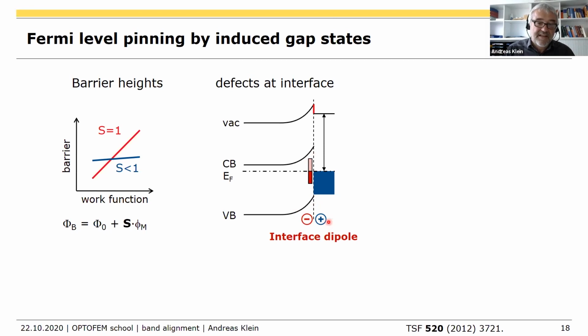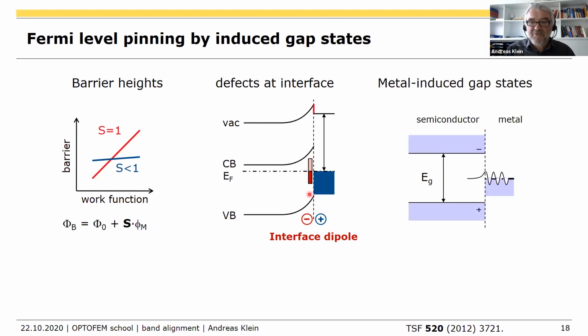If you have an interface dipole there, your vacuum levels are no longer aligned. You have a potential drop there, and this modifies the barrier height. If the density of interface states is high, the Fermi level at the interface will not vary at all. I will show this later. What's the reason for these induced gap states? Well, you take a semiconductor with a band gap and you take a metal. Now your metal has this work function, let's call it just phi. This is the work function of the metal.